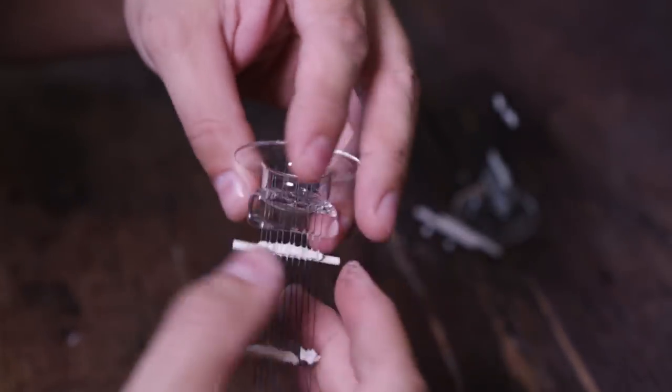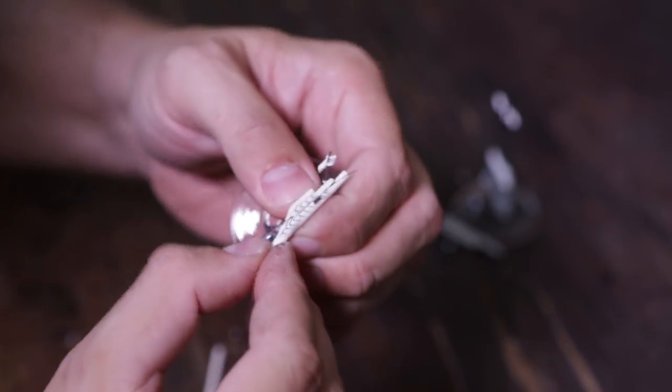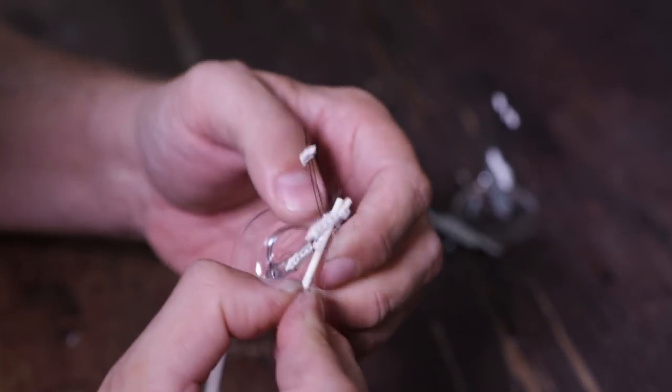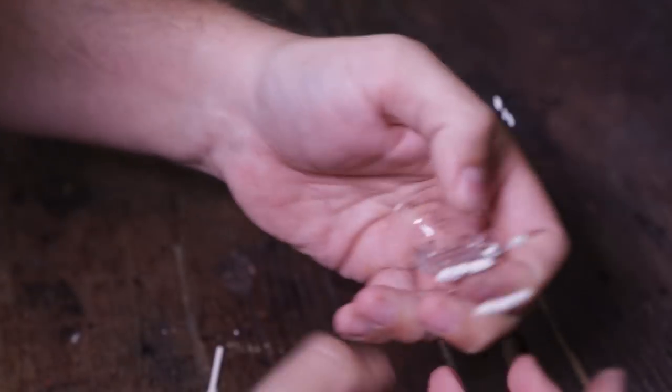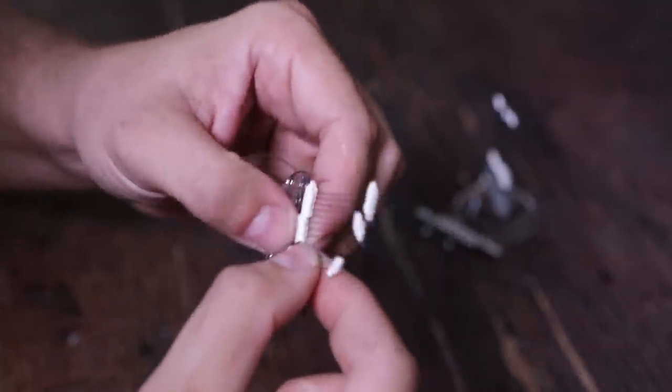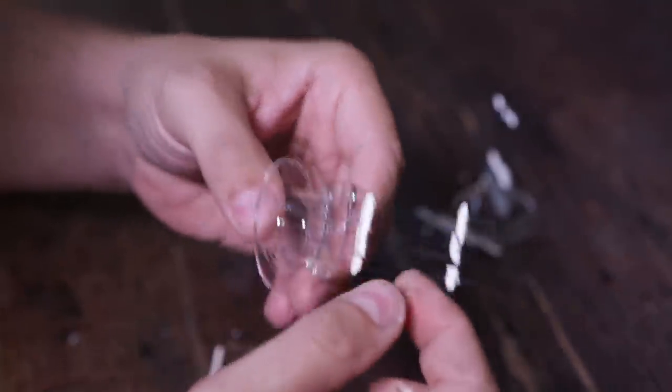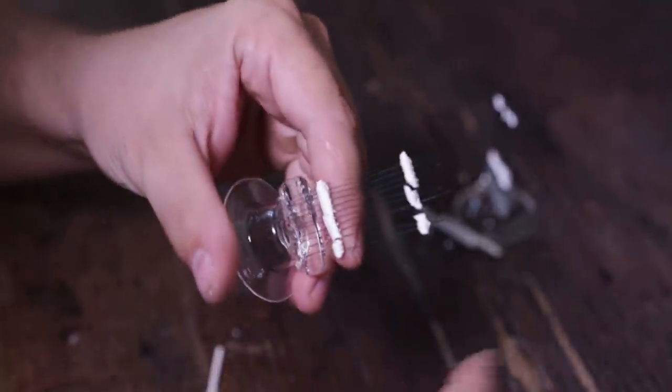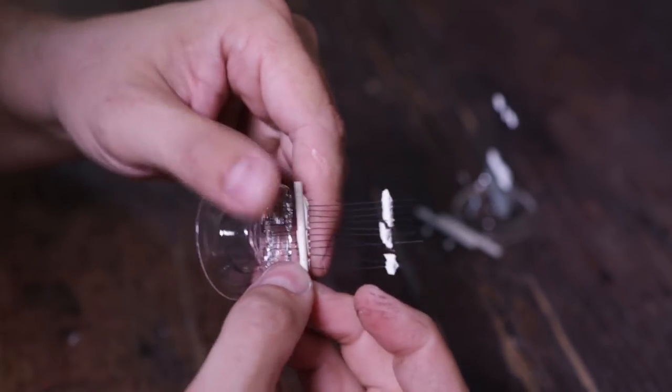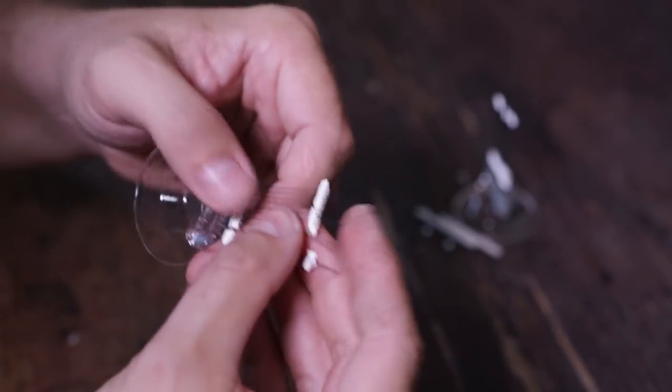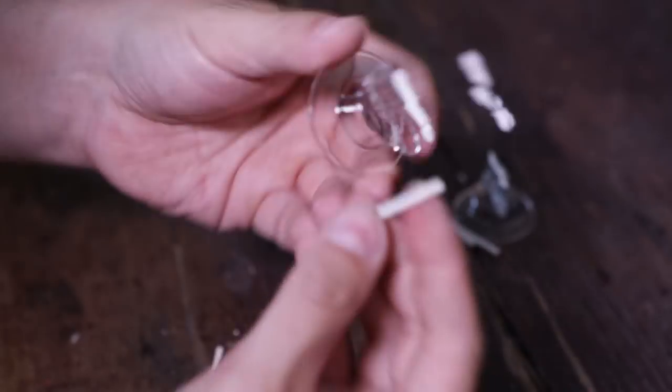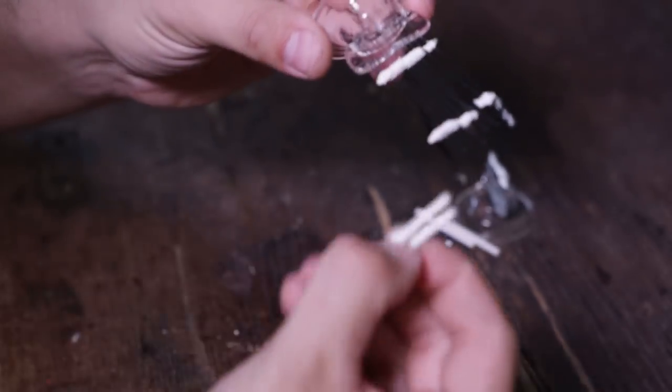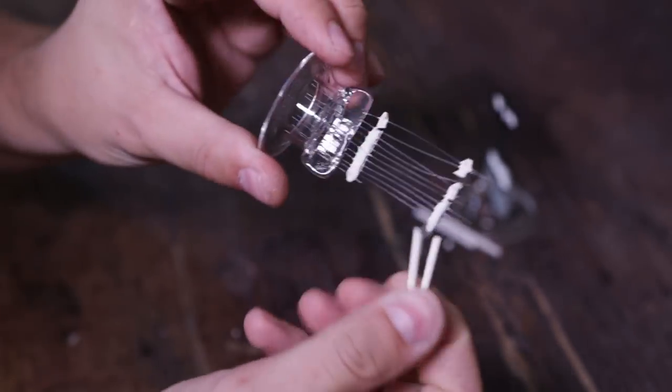I had to pull really hard on the glue, and the glue is still not the hardest as it can be because it was not cured at the maximum recommended temperature to get the best tensile strength. I think this will work. We will start using the alumina tubes with this glue.